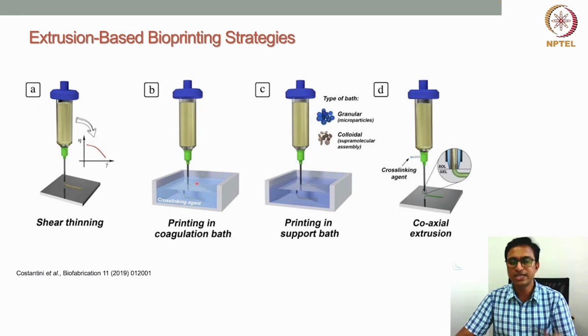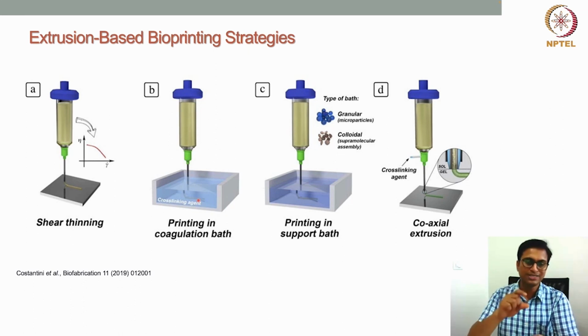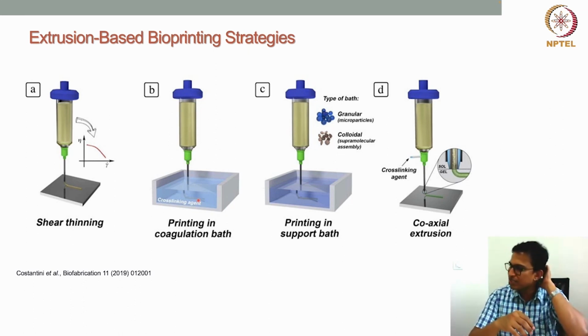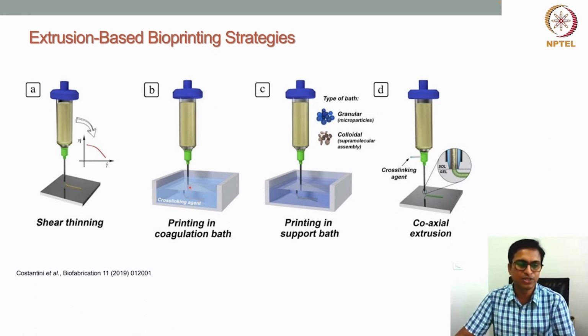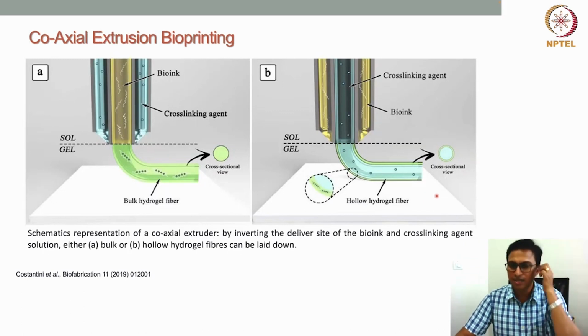The only difference here is when we insert the nozzle inside a cross-linking bath and print, the whole needle is exposed to the cross-linking agent. Sometimes what happens is clogging of the nozzle due to over cross-linking, which can be a limitation when we print the structure inside a cross-linking agent. But when we coaxially extrude both hydrogel material and cross-linking agent, we can overcome that challenge, and the printing can also be very good. So a detailed view of the same thing is given here.